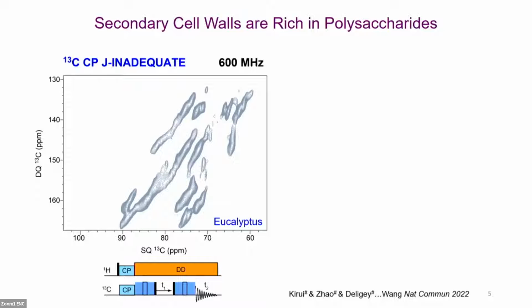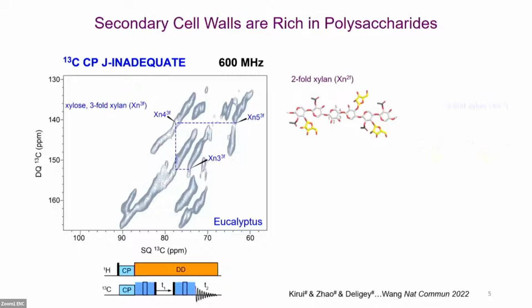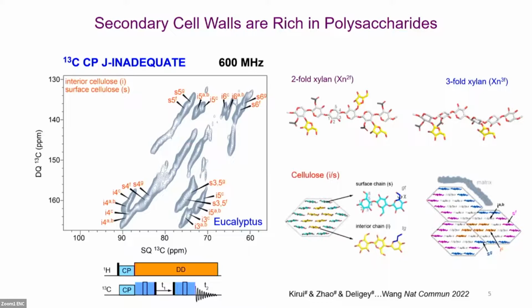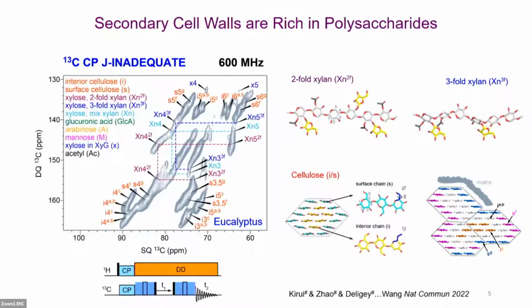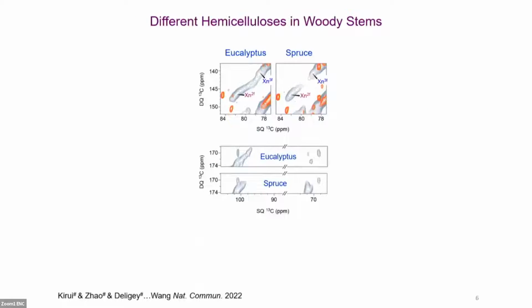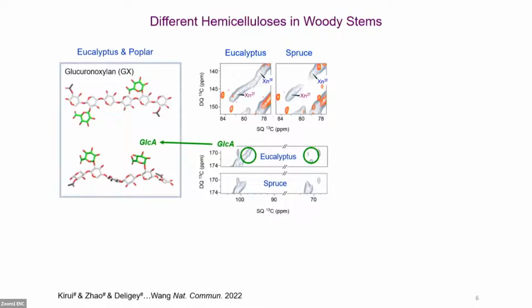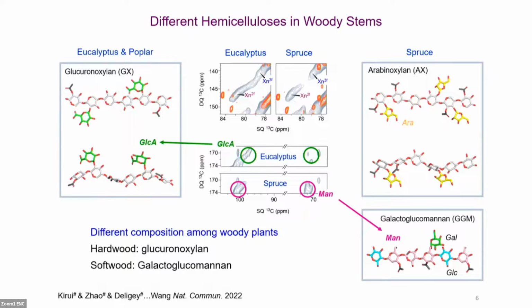Firstly, we run the refocused J-INADEQUATE experiment. From the spectrum, we can clearly see the two-fold xylan, the three-fold xylan, and the cellulose information, including the interior one and the surface one. Besides, we can also detect other carbohydrate information. From the INADEQUATE spectrum, we can also observe the different hemicellulose composition across the wood species. For example, the glucuronic acid only shows up in the hardwood spectrum, and the mannan is a unique component in the softwood.